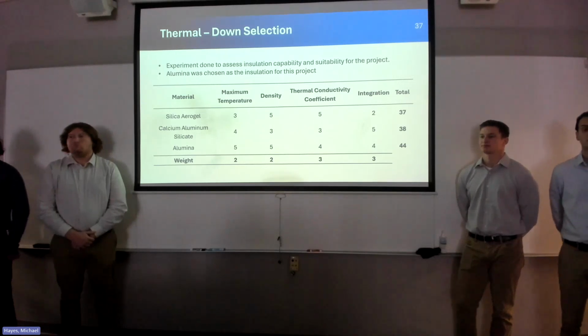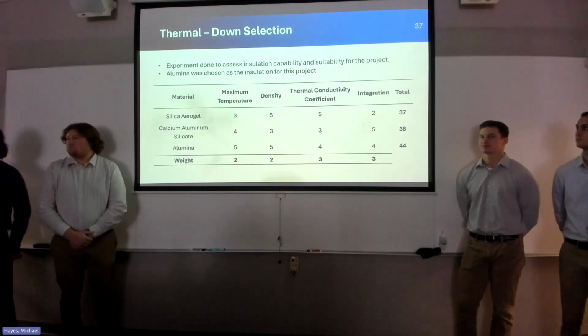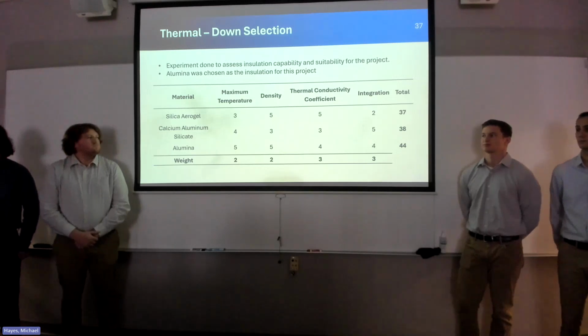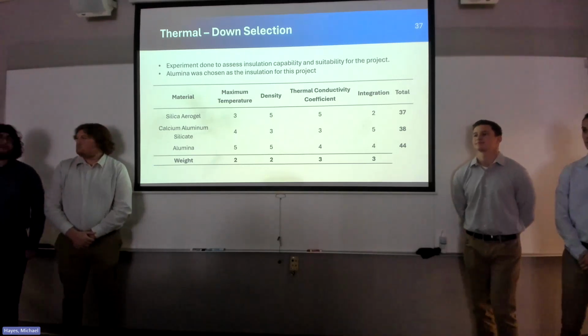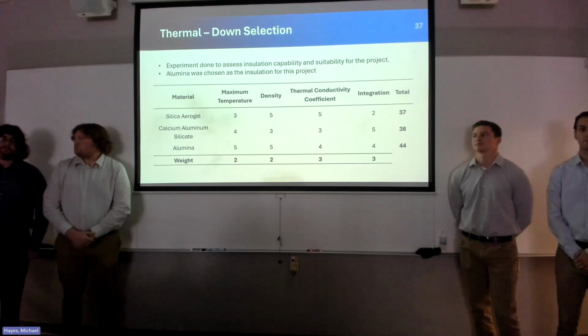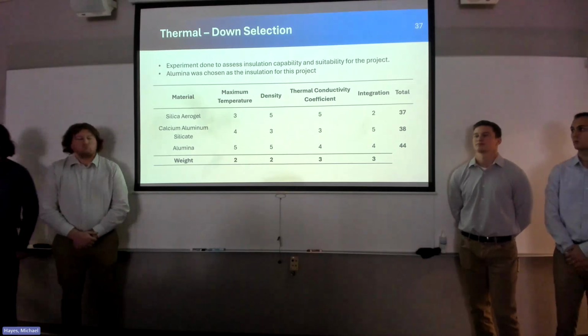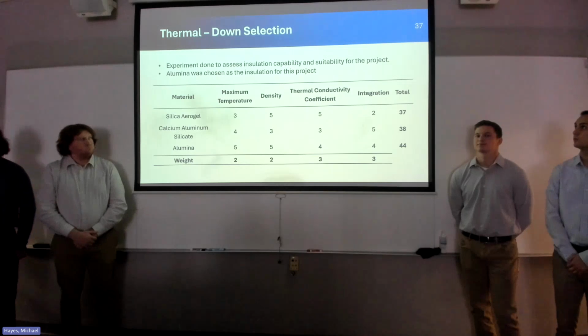And while silica aerogel was the best at insulating, it was not the one I wanted to choose, simply because being able to physically handle these materials showed me that it was tough to work with, it made a mess, and frayed really easily. Therefore, alumina, which worked a lot better, was the one chosen for this project.